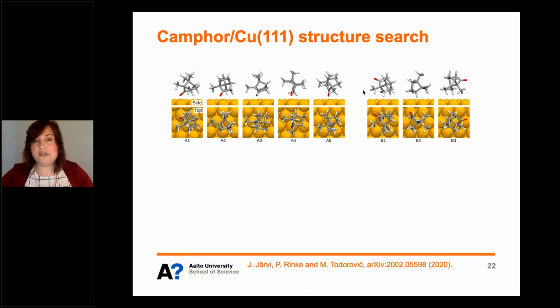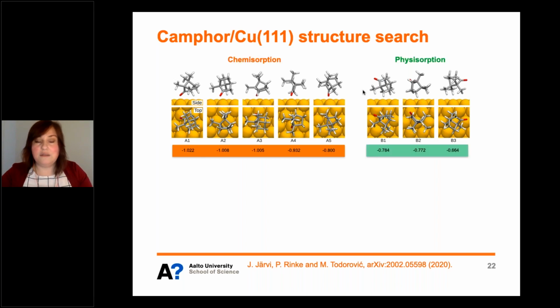So here's an example of camphor on copper 111, where we did exactly the same. We did a structure search in 6D, and then our student Yari extracted all the minima, and he found 8 different structures come out of this landscape. And we found 2 categories. The one on the left has the oxygen always pointing down, and the one on the right has the oxygen pointing up. So when we looked at their energies, it was clear the ones on the left were much lower in adsorption energies. So this is likely chemisorption, and the ones on the right were physisorbed. And this was indeed obvious when we looked at their partial charge.